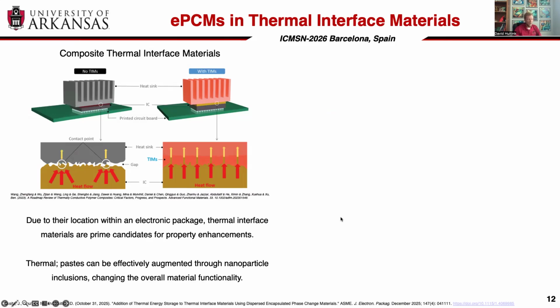A second area that I wanted to touch on briefly, as far as another application, is thermal interface materials, or TIMs. These are used at interfaces of essentially devices and heat removal technologies. So it could be a heat sink or a cold plate. And they exist to reduce the thermal contact resistance between the two surfaces. So typically these are greases or gels that have low viscosity that can fit into small asperities in the surface, and their main function is to provide a conduction pathway to the heat sink.